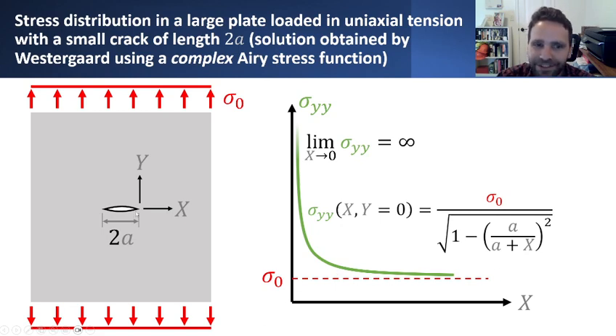But as you approach the edge of this crack, the stresses increase. In the case of the plate with the hole, the stresses increased to a finite value that was proportional to 3 times the average stress. In the case of a crack, however, the stress zooms off to an infinite value as you approach this crack tip location. And that's kind of unsatisfying, largely because we know that there's no way that the material can sustain an infinite stress. That's just unphysical. It's a limitation of the way that we've developed our theory of elasticity, by assuming linear elastic material behavior. There's no way for the material to sustain these infinite stresses.